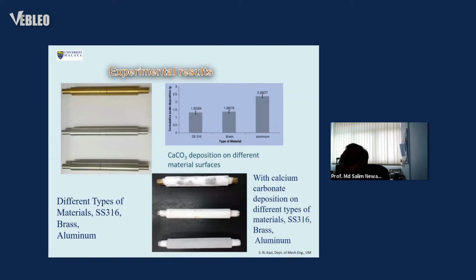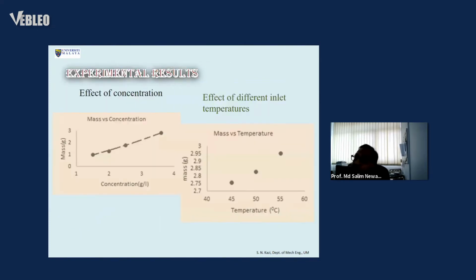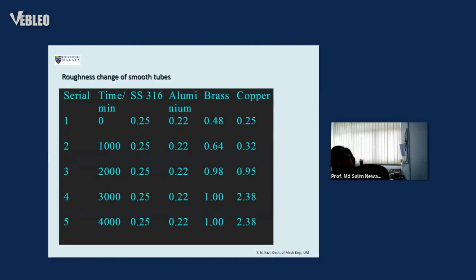So we find that if the surface is more conductive, then there is more deposition. For aluminum, brass and so on, the deposition is recorded according to their conductivity, along with the effect of concentration. If the concentration of the solution increases, there is more deposition, and the higher the temperature on the surface, the more deposition. But the biggest challenge is that when there is deposition on the heat exchanger surface, it introduces corrosion. Due to that problem, the fouling run cannot be reproduced, so we have to change the specimen to get back to the initial state.